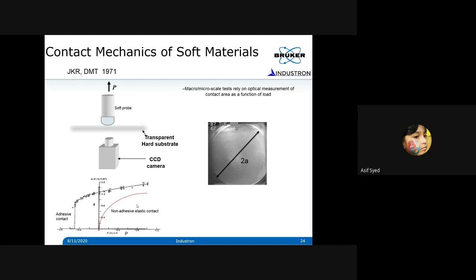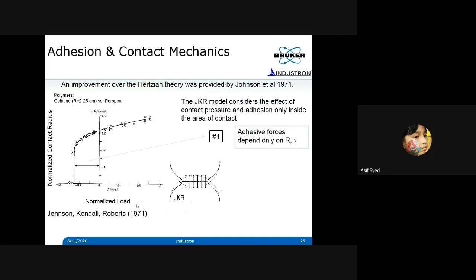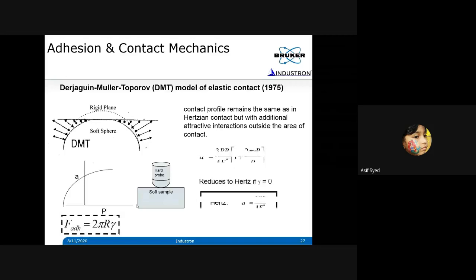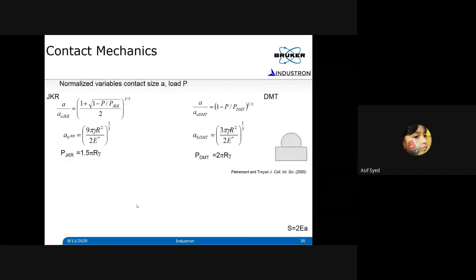When we tried to do this in the beginning, I found some problems. This is part of my PhD, my postdoctoral work. So we went back to Ken Johnson, who developed these theories. Then he tweaked his theory to match what we found, and we were able to modify it so that it works even at nanometer length scale. So we have those models already there, which take care of the adhesion in contact. Once the adhesion in contact has been taken care of by the model, you can use this load displacement curve and extract the mechanical properties. Not to bore you, I'm going to skip some of these slides, and I'll go to one important slide that I have here.